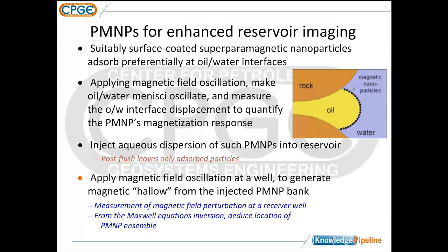The first idea of reservoir imaging we worked on, to detect the presence of oil in deep subsurface formation, goes like this. We first prepare suitably surface-coated superparamagnetic nanoparticles that adsorb preferentially at the oil-water interface. And then, applying magnetic field oscillation, we can make the oil-water meniscus in porous media oscillate, and we can measure the oil-water interface displacement to quantify the magnetic nanoparticles' magnetization response.